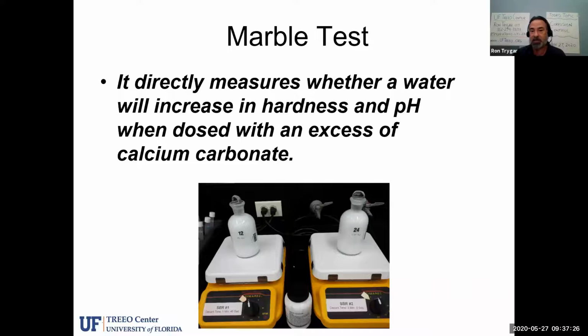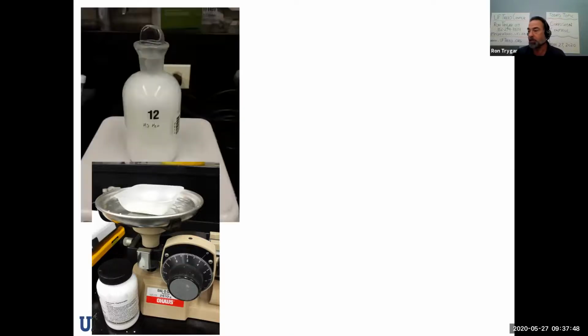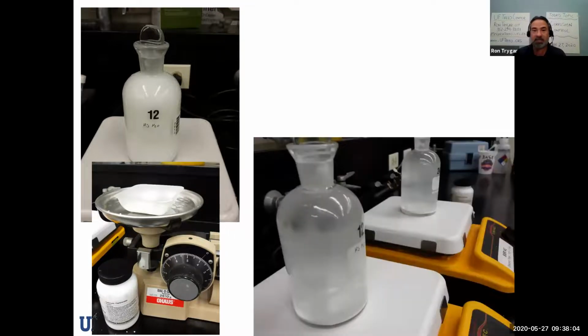So in this picture you see a couple of glass bottles. These are known as BOD bottles, bottles with stoppers on them to prevent carbon dioxide from getting in, but they've been dosed with the calcium carbonate, and it makes that white milky looking solution. So the marble test is essentially where we would weigh out a small portion of the calcium carbonate and add it to a bottle of water with a stopper on it to prevent CO2 from getting in. We would mix this thoroughly for several hours, maybe half a day or more, and then we would let it settle out overnight, maybe 8 hours or more.